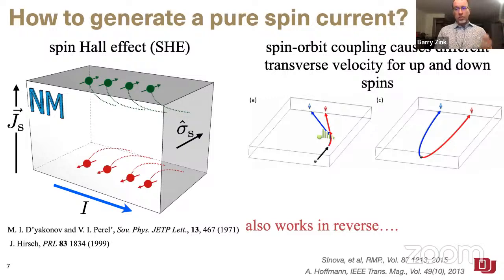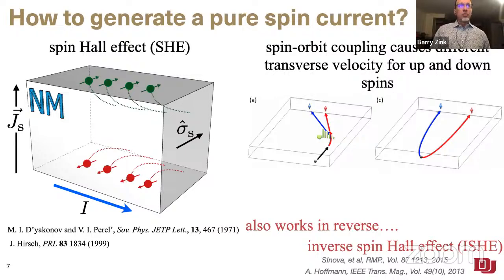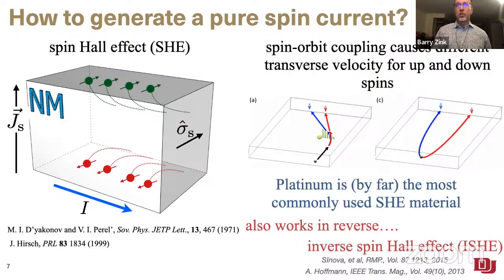Note, very importantly, this also works in reverse. So if you could get hold of a spin current in a different way, inject it into this material, say from the bottom, then you just have to flip all of the arrows around, and you end up having all of the charges pile up on one side of the material. So that's called the inverse spin Hall effect, and it's very important because it gives us a way of detecting spin currents that flow into material. All right, so that's pretty basic still. Hopefully everybody is following along with this.